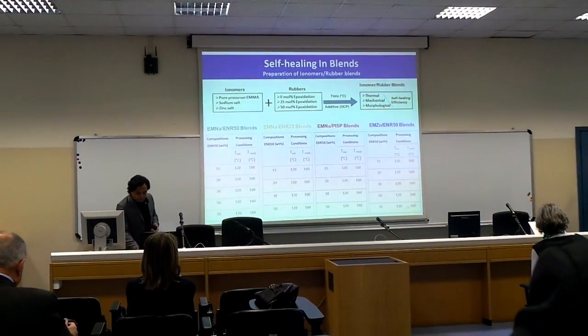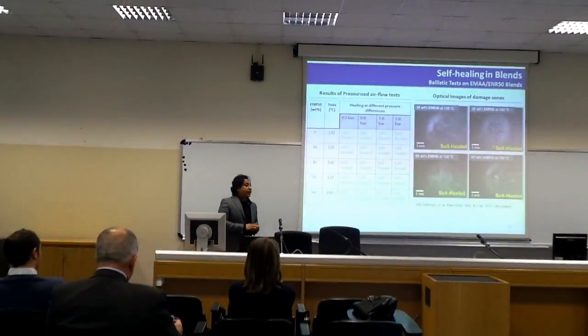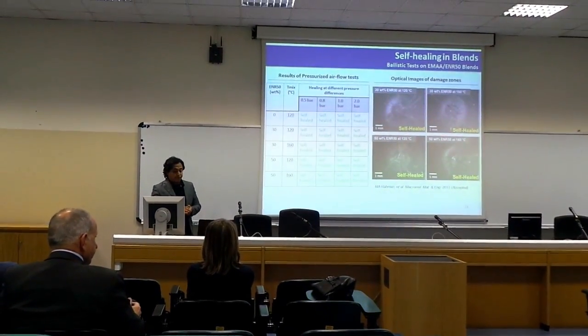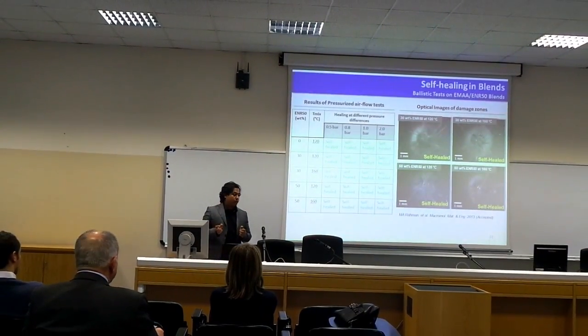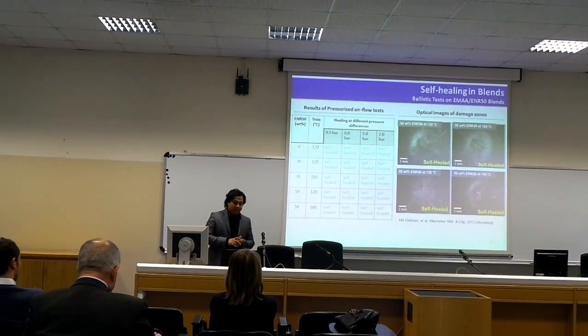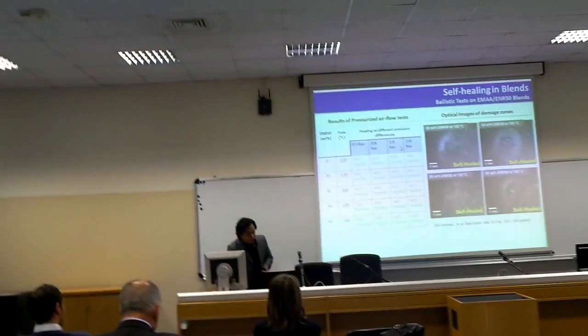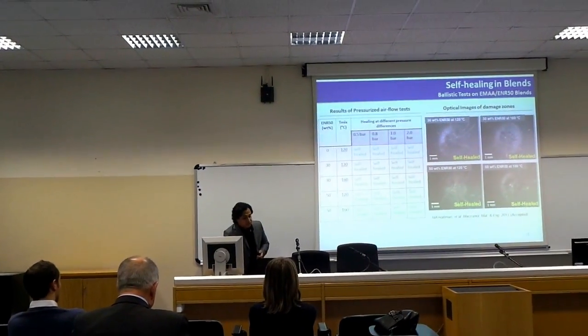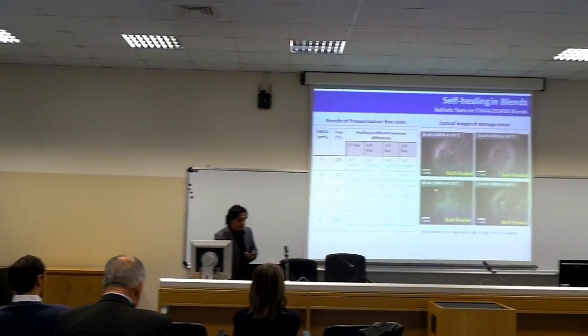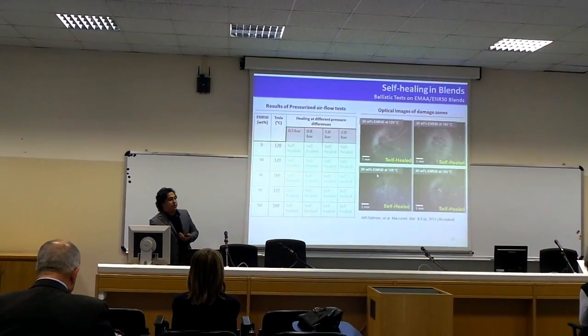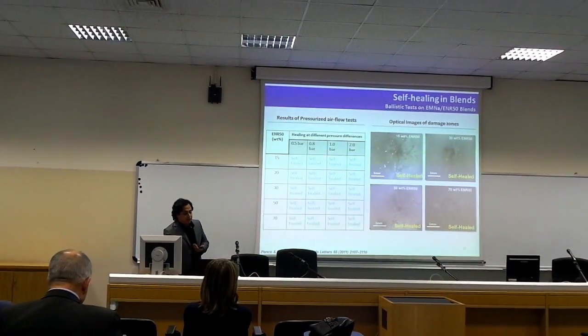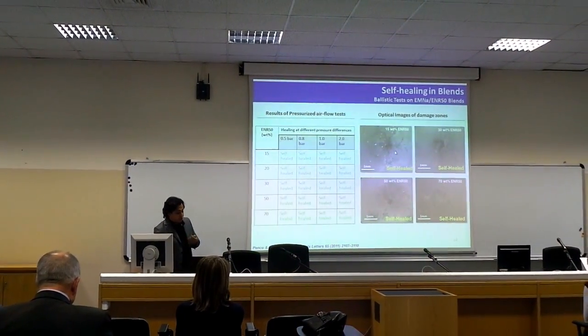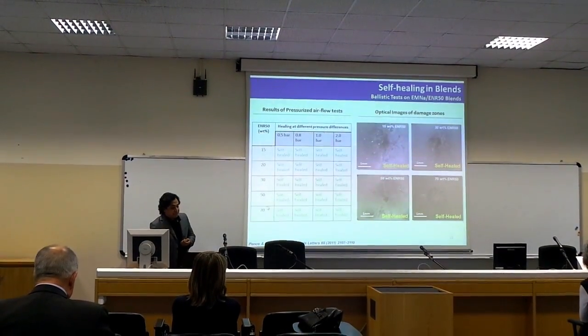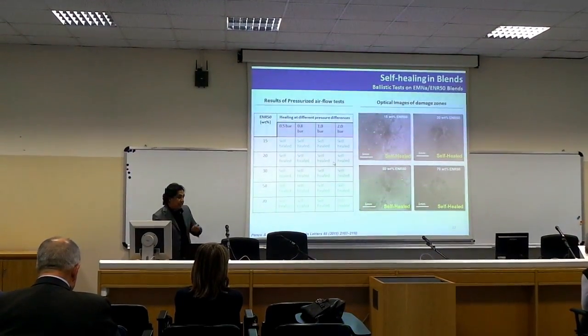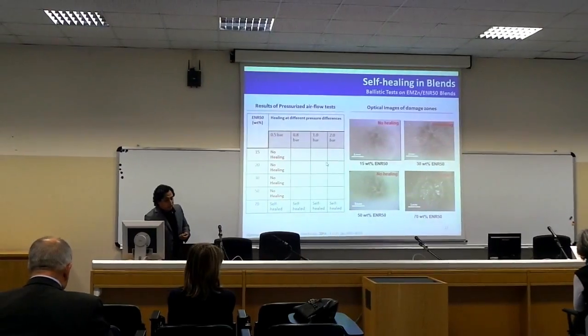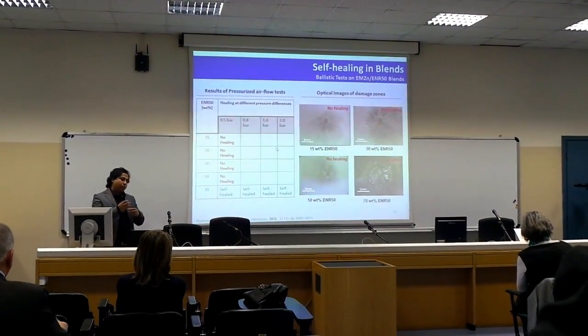And in the final product, of course, we have a wide range of thermal and mechanical properties with different levels of healing efficiency. At first, I studied the pure copolymer and ionomer and epoxidized natural rubber 50 blends. And you can see that in the pressurized airflow test, all the compositions showed self-healing behavior, irrespective of their processing conditions. And in the sodium and rubber blends, also in this case, I observed complete self-healing with high healing efficiency at each composition of the blend. However, when I blended zinc ionomer with epoxidized natural rubber